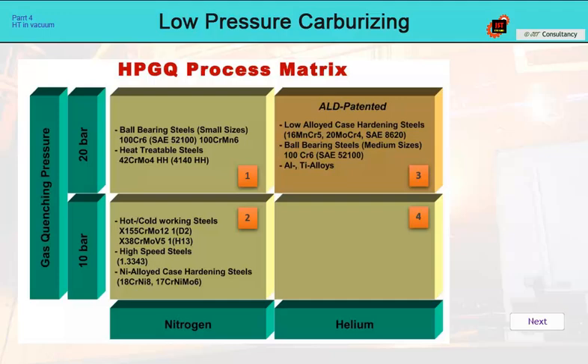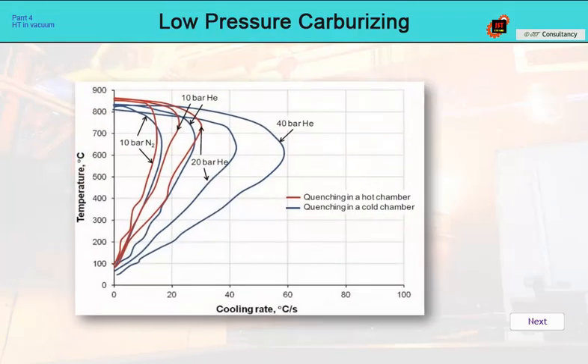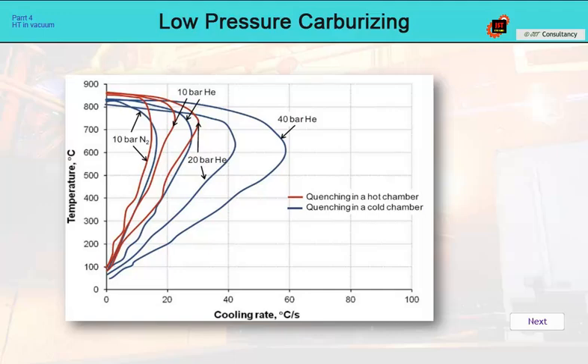ALD has published this table, which can help a lot in our decision-making. With Category 1 steels, we have to be very careful if we choose nitrogen. Category 2 steels will always be hardenable in nitrogen, but these are mainly tool steels. In Category 3, there are steels that can be quenched in helium, but not in nitrogen.